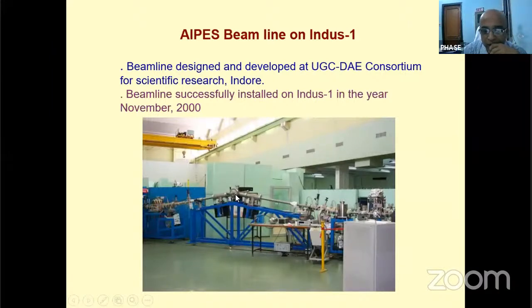And then this monochromatized beam is focused on the post mirror. Another mirror chamber is there, because the beam is coming in the straight, horizontal direction, and it is bent by the pre-mirror at 4.5 degree. Here, the mirror is in the opposite direction. It will bend that beam downward, so the beam is reflected downward, and the mirror is again at 4.5 degree.